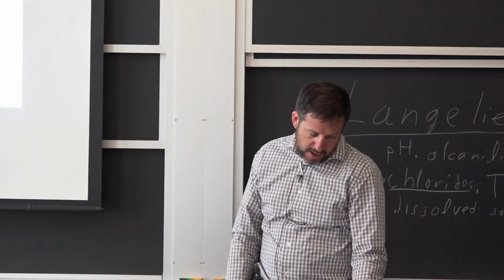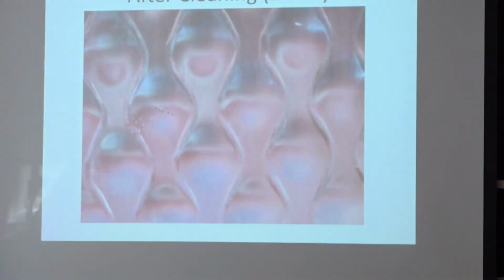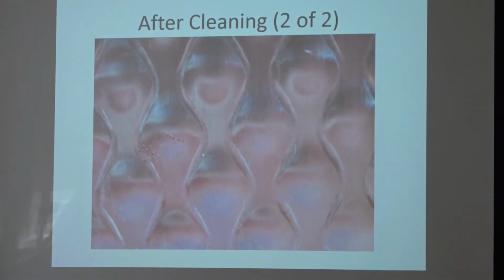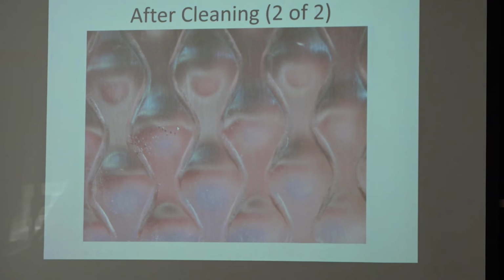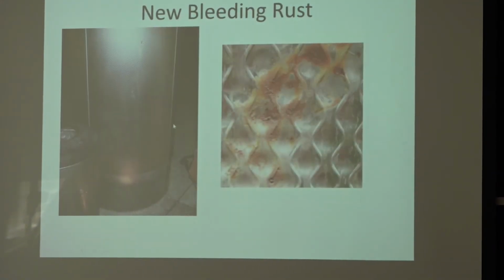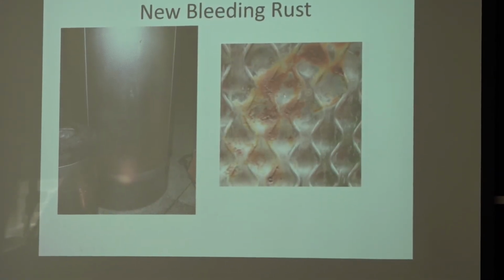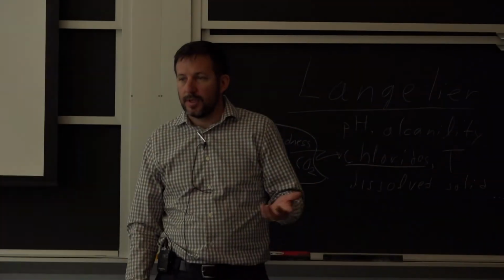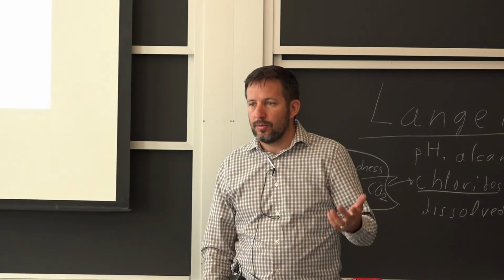But the big problem on the project was that even after the best cleaning they could do, they still had those holes, and nobody told them. What happened after, and that's when we got called in, was it started rusting again. Okay, so this second time that it rusted, it wasn't the cleaner, right? It's just like we discussed, it was these little holes that were in there, and the chloride environment, close to the beach. A lot of moisture coming in to